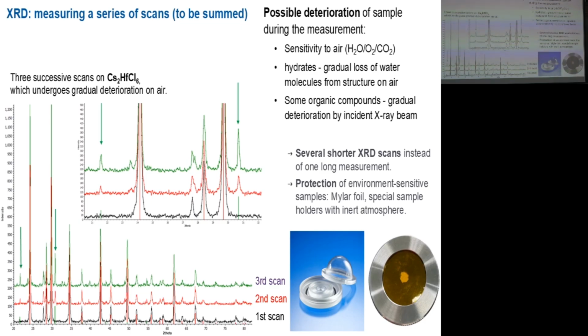Also, some samples might become decomposed under the irradiation by X-ray, or some samples will lose their water. So I would recommend to do the measurement as a series of rather fast, short scans that you can later sum. So typically we are measuring 5 to 15 scans, or rather fast scans, and then if we don't see any change, we can sum them.